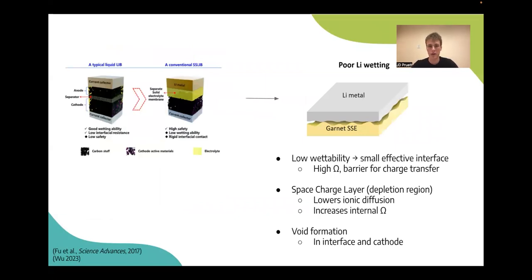So in a normal lithium-ion battery, right, we've got sort of slurry on either side of the separator, which makes a nice contact with the separator. In a solid state battery, the issue that we get is one of what is called wettability, or basically the ability for a liquid to maintain contact with a solid, or potentially in this case, two solids to maintain contact with each other. Obviously, if you imagine, it's like if you put two big pieces of metal on top of each other, they're not going to be perfectly touching in all planes. And so you get these gaps in between. And these gaps mean that the effective interface between the electrolyte and the anode, lithium metal in this diagram, is actually quite low, which makes for high resistance and means it's really hard to have ion transport across that boundary.